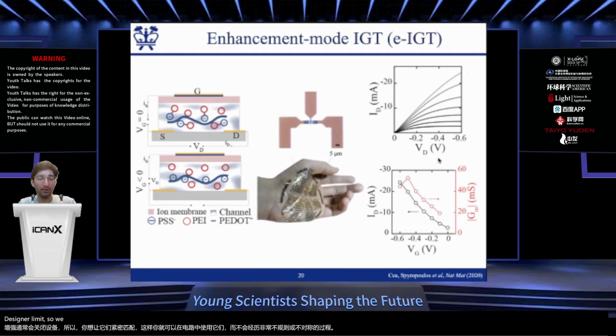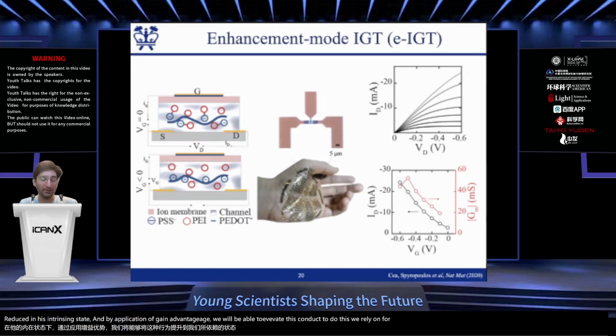So we hypothesized that the next step to create this enhancement mode structure would be utilizing a channel material that is reduced in its intrinsic state, and by application of gate voltage, we would be able to elevate its conduction. To do this, we rely on polyethylenimine, PEI, to chemically reduce our PEDOT:PSS channel material. And by application of negative potential, the PEI releases the bonded PSS in its intrinsic state, allowing the formation of PEDOT:PSS, hence the conductivity increases. So looking at these IV curves, the higher the gate voltage, the higher the drain current.